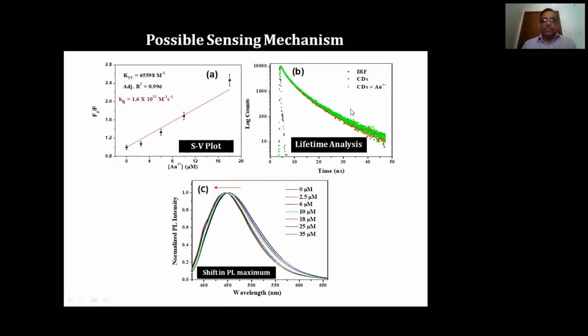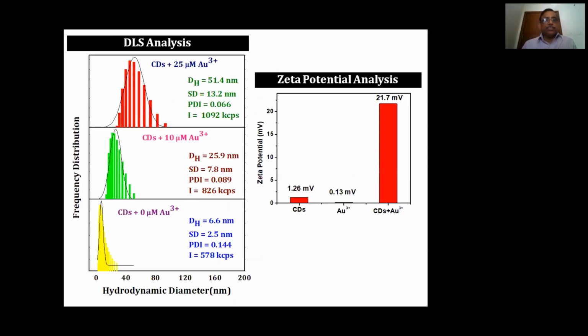And maybe the sensing mechanism also we are trying to look at. Your lifetime remains the same - lifetime quenching is not happening, only the fluorescence intensity quenching, which tells us it's again a static behavior of the quenching of the luminescence by the gold. DLS gives us information about the sizes and the negative charge, and zeta potential gives information about the charge on the surfaces that we see.